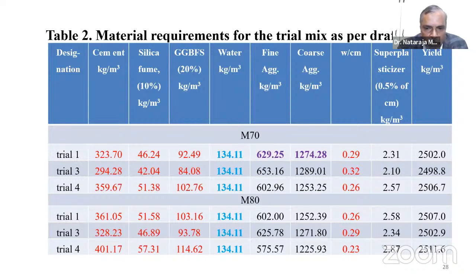Okay. Now kindly see here, I have put some information here. If you are designing an M70 concrete, this is the first trial mix, what you get from the first trial. And anyway, you have the computer program where the additional trial mixes can be exercised. And based on the result of the first trial, we will be doing the mix design of trial 3 and 4. This has to happen inside the concrete laboratory. And of course, kindly see the water cement ratio. In the first case, it is 0.29 plus or minus 10%. And for M80, the first water cement ratio is 0.26, what I get from the basic mix design. And with plus or minus 10%, the two water cement ratios I will be having.